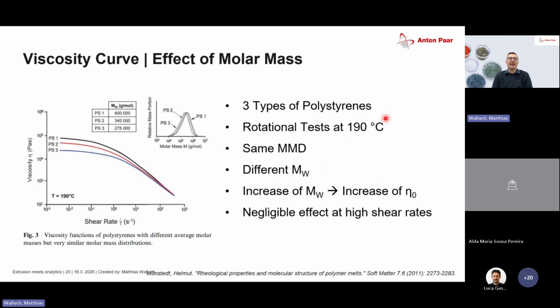Now the question is, what can I see out of my viscosity curve? In principle, we can compare materials with different molecular weights or molecular weight distributions. Here we see three materials, they are basically the same, but the molecular weight is shifted from PS1, polystyrene 1, with a high molecular weight, to PS3 with a low molecular weight. And as we can see, the shape of the curves changes, especially in the beginning, where with a decrease of the molecular weight, the zero shear viscosity also decreases. If we go to higher shear rates, the material behaves basically the same, so it's not that high an impact. But at low shear rates, the impact can be very, very high.